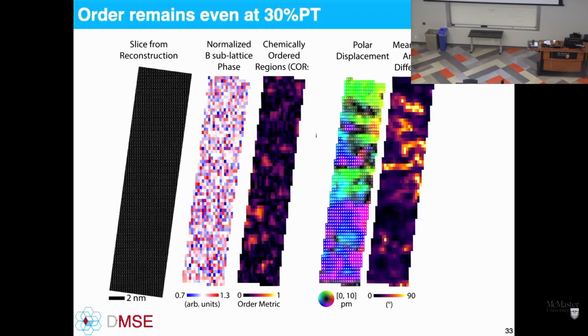This is found by using basically the phase on the magnesium, niobium, and titanium columns. And you can see local regions of order where you have bright red, blue, red, blue, red, blue over here. This corresponds to a local chemical ordering of magnesium-rich, niobium-rich. The weaker the phase, the more magnesium. The stronger the phase, the more niobium at that position. And so we can map this out and actually find that this agrees very well with what we'd expect from the calculations. So in many ways, the experiments validated the theory, but the theory also was validated by the experiments, that we can really find these sorts of distributions in both.